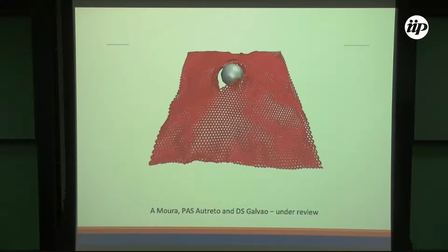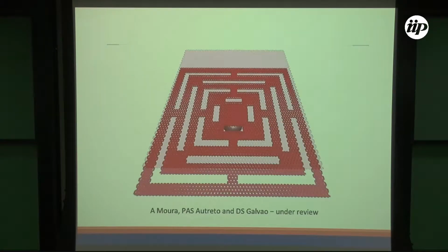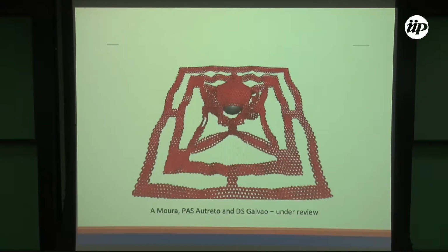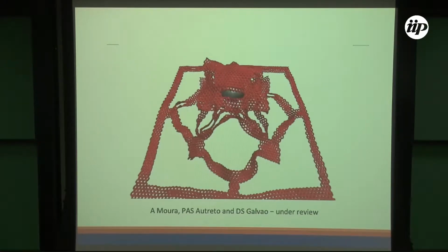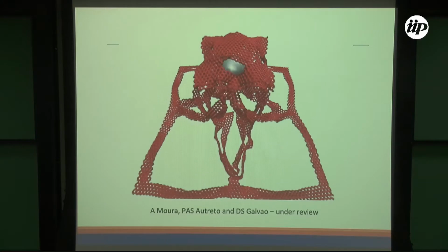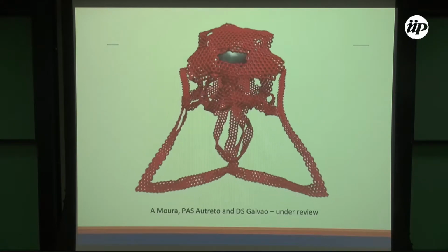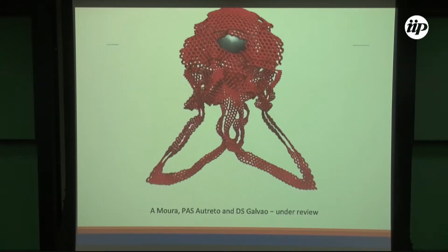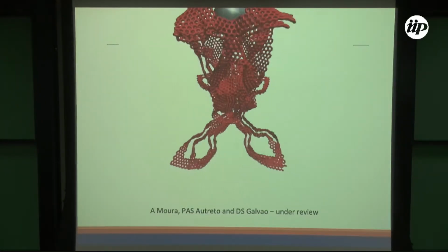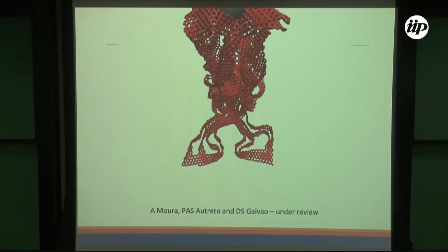This is a very surprising result, again using ballistic impact. This is just graphene. It breaks. If you shoot with the same kinetic energy at the same size, because you have this kirigami topology, it can stop the bullet. So you have the same dimensions, less mass, but it can stop the projectile better than the full structure. This is just because of the topology.